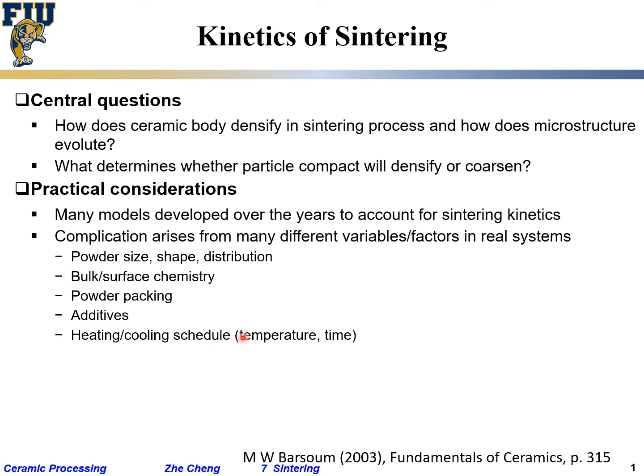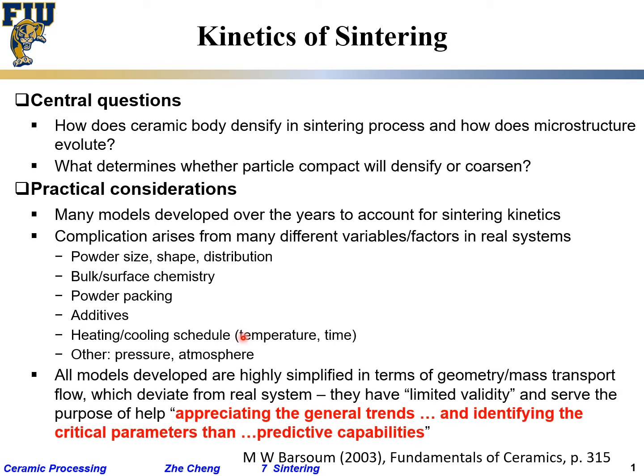The heating and cooling schedule is also tricky. We talk about isothermal sintering, but then we acknowledge it's not exactly isothermal because it takes time to heat up and cool down. Pressure and atmosphere are also very tricky to control. The atmosphere outside versus within the bulk of a ceramic body may differ, and with hot pressing you cannot guarantee the same pressure throughout the material due to friction and body size.